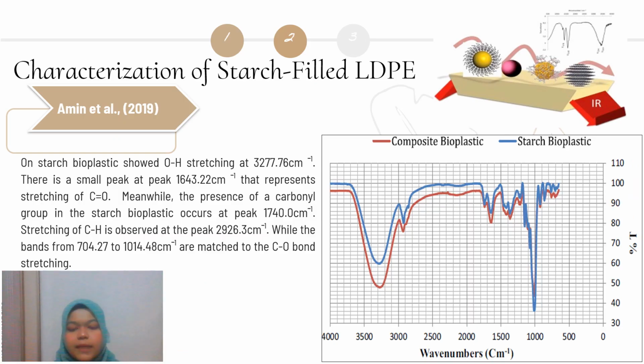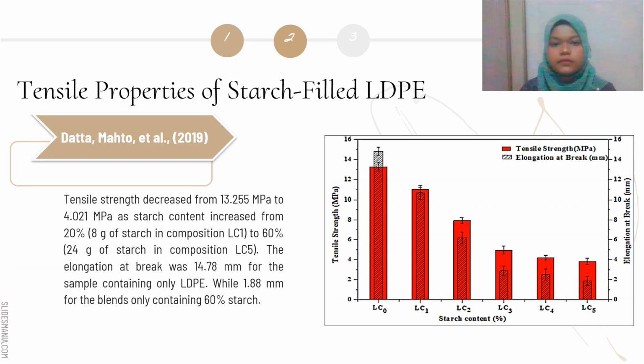A previous study by Amin et al. 2019 on starch bioplastic showed OH stretching. There is also a small peak that represents the stretching of C double bond O. Meanwhile, the presence of a carbonyl group in the starch bioplastic also occurs. Stretching of CH is also observed, while the bands from 704.27 to 1014.48 per centimeter are matched to the CO bond stretching.